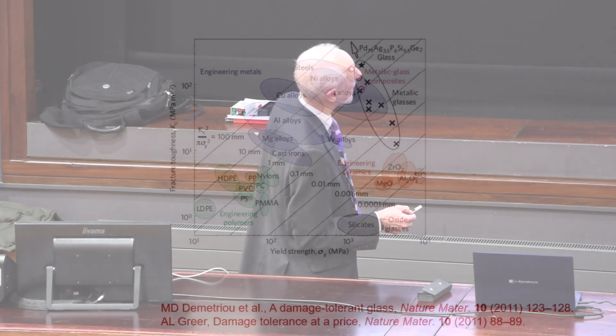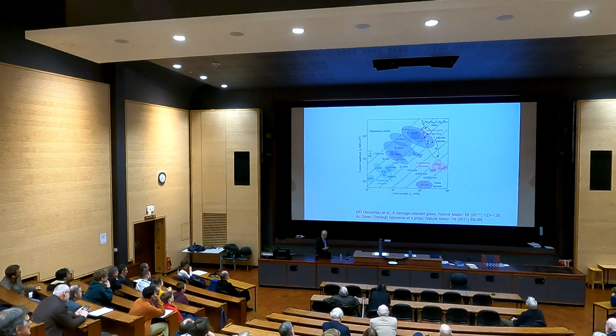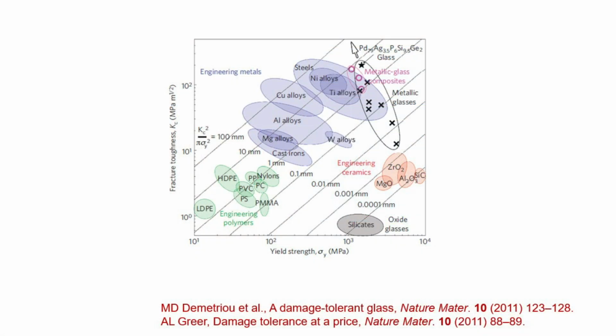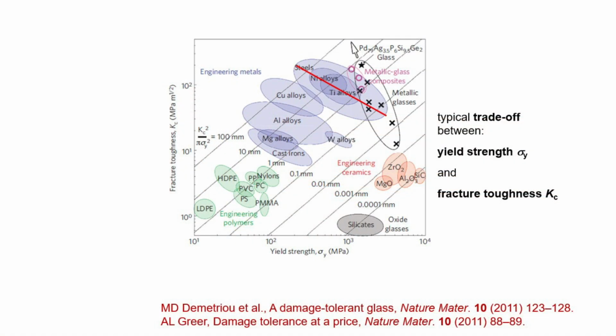So where does a metallic glass sit, and how should we look at this in general? Well, in general, to avoid failure by cracking, you need to get the crack to be blunt, and that means you need to get some plastic deformation. So you more or less have one or the other. And this is the typical trade-off. Some people will be familiar with how this works for steels, where you could take a hot steel, quench it, you get something very hard called martensite, but it's also brittle. And then you anneal it, you temper it, it becomes less hard, but it becomes more tough. So you have one or the other, basically. You have a trade-off.